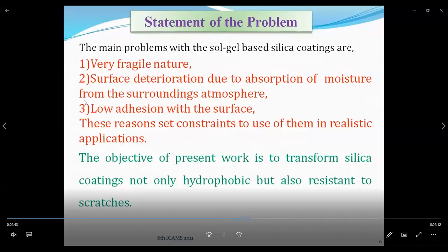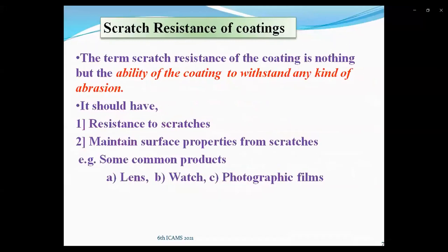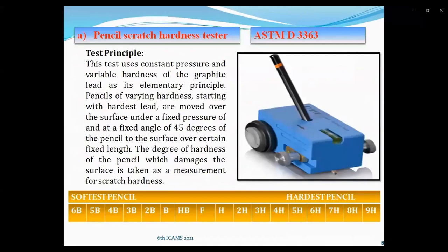Scratch resistance of the coatings is defined as the ability of a coating to withstand any kind of abrasion. It should have resistance to scratches and maintain the surface properties from scratches. Further, we have measured the scratch hardness of the coatings with the help of a pencil scratch hardness tester as described by ASTM D3363.